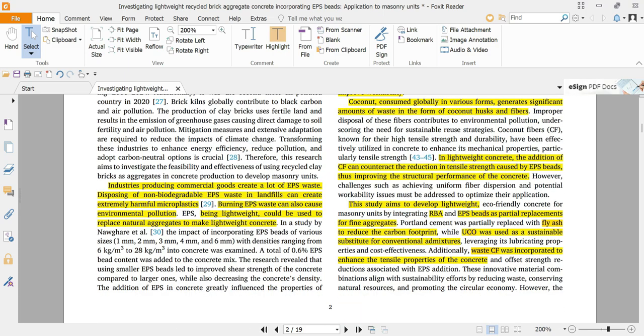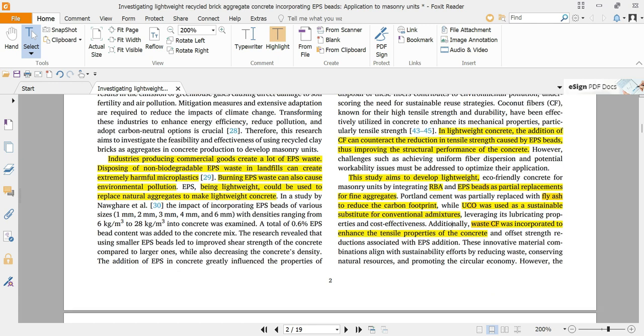This study aims to develop lightweight eco-friendly concrete for masonry units by incorporating recycled brick aggregate, EPS beads as partial replacement of fine aggregate. It also uses fly ash to reduce the carbon footprint as a replacement of cement. It also uses the used cooking oil as a sustainable substitute for the conventional admixtures, which are very costly. Moreover, it uses coconut fibers to enhance the mechanical properties of the concrete, especially the tensile strength.